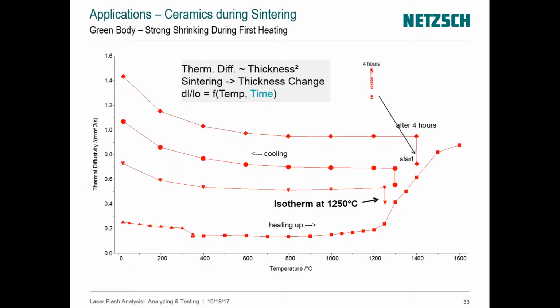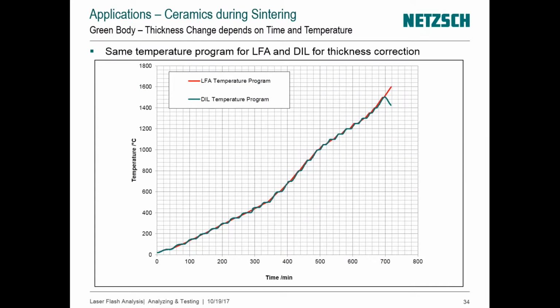And most important here is that in that particular case, we are bringing the information obtained from a dilatometer to bear too. So the measured or calculated diffusivity in this case is the correct diffusivity. In other words, we account for the thickness of the specimen. Very important for ceramics. In this instance, we are showing the temperature profile that was obtained with a dilatometer, and we will be trying to match this temperature profile with our LFA too. So we program our LFA with the various temperature segments, in a way so as to mimic the way the dilatometer was used. By the time we use this information in the calculation, the true diffusivity is actually correct. It's a very important point.